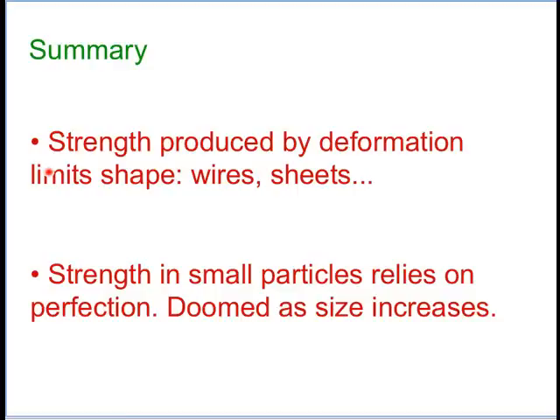if you try to produce strength by physical deformation, then you can only produce wires or thin sheets. If you try to produce strength in small particles which relies on perfection, then that is doomed as size increases. So these are not good methods of making engineering materials out of which you are going to make engineering structures.